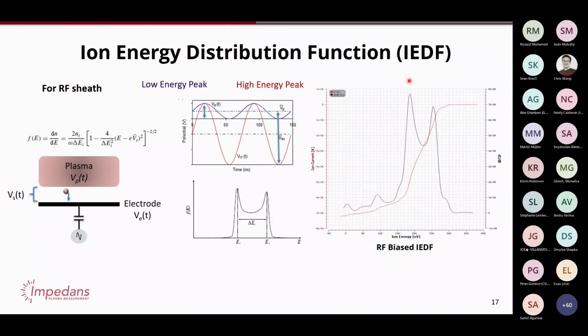But here's some fairly typical data. I think this might have been 2 megahertz. So you have your high energy ions, your low energy ions. In this situation, the pressure was high enough that the plasma was sort of collisional. So these 2 little peaks you see here, in black, are actually echoes of these. This is cases where ions traveling through the sheath had a collision, lost some energy, or passed their charge onto something that was stationary or practically stationary, and so there's a momentum difference. So then you have these little peaks based on those collisions. So these are the 2 extremes of what you measure.